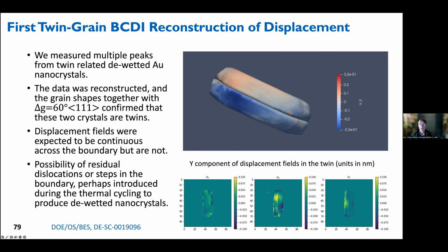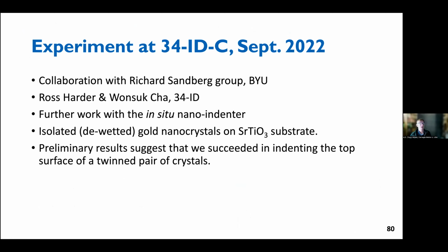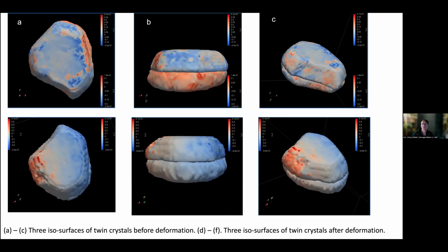And then very recently, meaning only last month, we went to 34ID with Richard Sandberg and company, hosted by Ross and Wonsuk. And we literally brought to bear a nano-indenter. So we found a twin pair of related grains, made sure that we could collect diffraction peaks, measured the twin pair, and then we poked at it with a nano-indenter. So these are isolated, in fact, de-wetted gold nanocrystals on a strontium titanate substrate. And we think that we succeeded. So in the following sense.